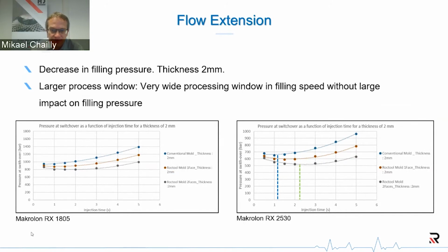Here we have the same 2 millimeter thickness for the disc. Again, if we take a look at the graph on the right, we can see in blue, in conventional conditions, we have an optimal filling time that would be around 1.1 seconds. And as soon as we want to inject in 5 seconds, we have a drastic increase in pressure at switchover because we have increased this pressure by 30%. That's typically the range of figures that Vito mentioned.